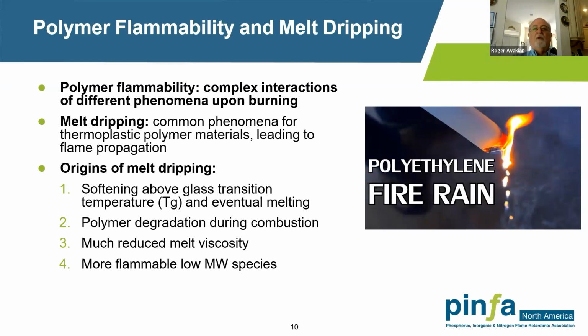But the origin of melt dripping is that when you heat up a polymer, you're heating it above either the glass transition temperature for an amorphous plastic or above the melting temperature for a semi-crystalline plastic. In both cases, the melt viscosity reduces or diminishes, and basically material can drip. You also get polymer degradation during combustion, so you're breaking the polymer down into smaller units, which again are less viscous and tend to drip. Both of these mechanisms reduce the melt viscosity, and the degradation also produces a more flammable, low molecular weight species.